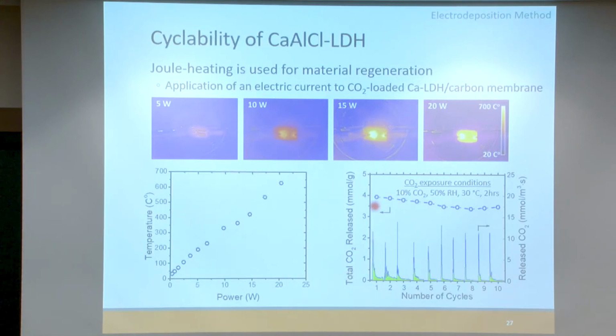What's shown here is how quickly the CO2 comes off during regeneration, where each of these green parts is about five minutes long. You see that within the 5 minutes, a lot of CO2 comes off right at the beginning, and then some of it comes off later on, where if you held for longer, more CO2 would come off. But within 5 minutes, we saw a good regeneration of the material.